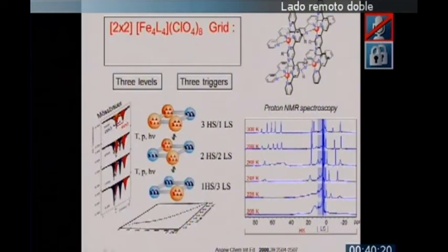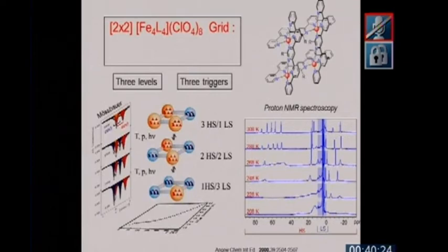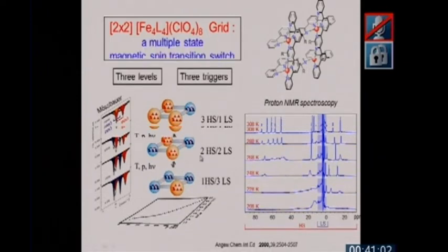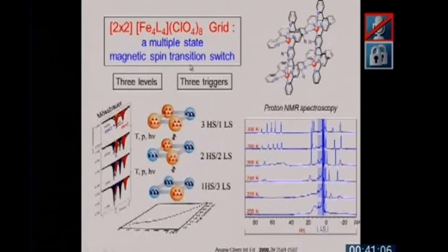So such a system can have 5 spin states: all the ions low spin and all the ions high spin, and between them 3 spin states with 1 low spin, 3 high; 2 low, 2 high; 3 low, 1 high. And a study done by the group of Philipp Gütlich in Mainz showed that in addition to the change in magnetic state induced by temperature, like shown in the NMR spectrum, one can also induce such changes by pressure or by light. So one has a rather interesting and unusual case where you can induce magnetic spin transition between 3 levels using 3 different triggers. 3 different triggers can be used to change the magnetic state of the system.